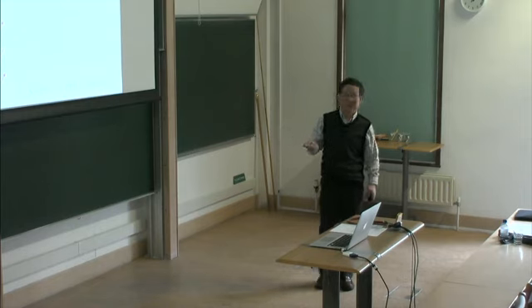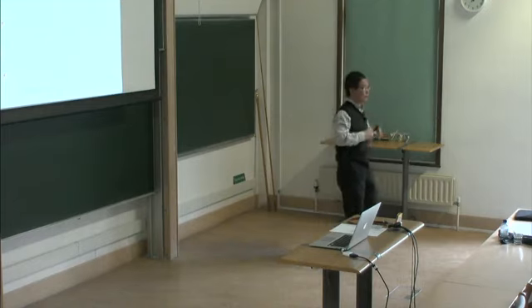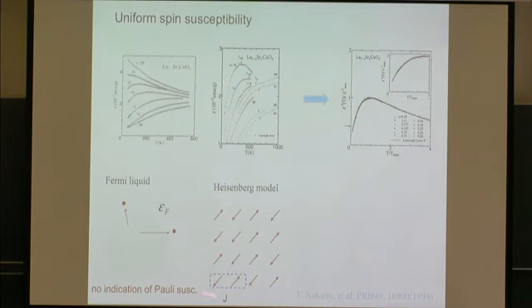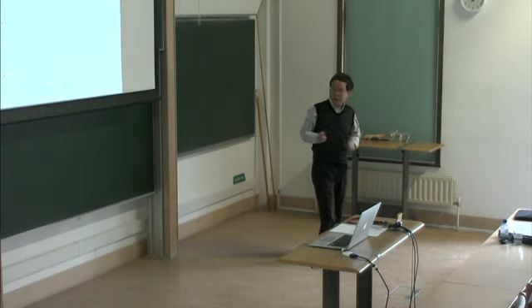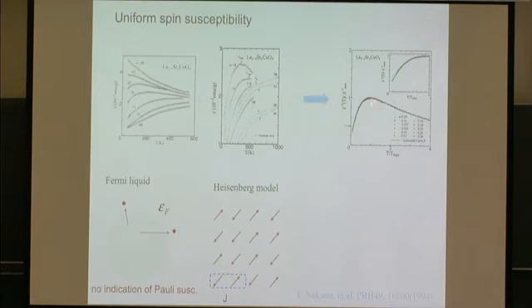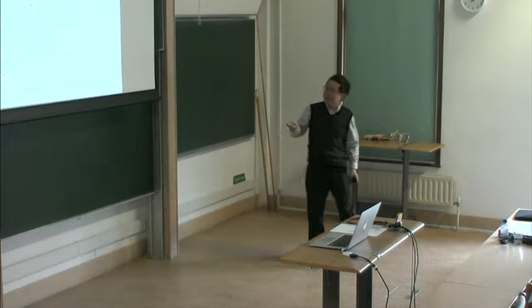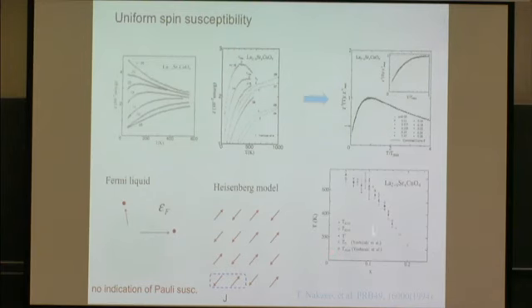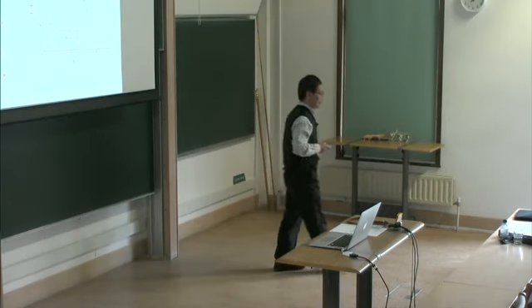Instead, it's well described by this Heisenberg model where you have local spins which interact with each other through nearest neighbor superexchange J. But this J will decide this peak value, so you will have strong doping dependence. This effective coupling as a function of doping decreases monotonically. So this is a temperature. Below this temperature, above Tc, you see the suppression of uniform susceptibility, which people call the pseudogap behavior, one of them.